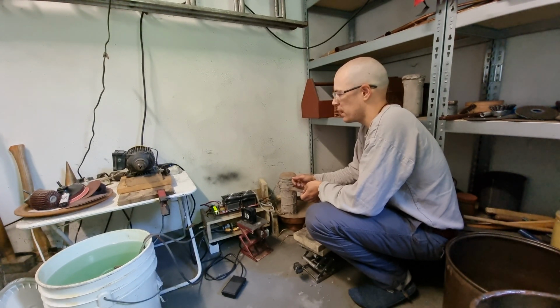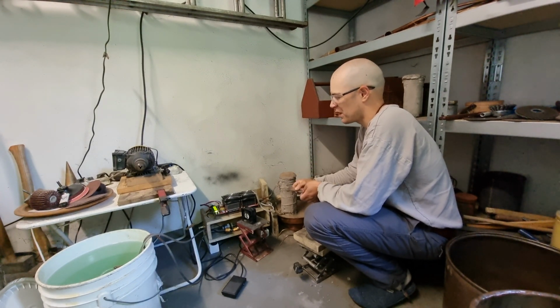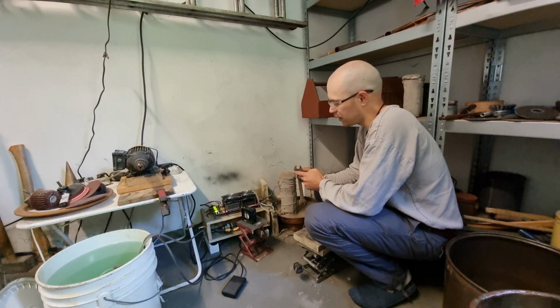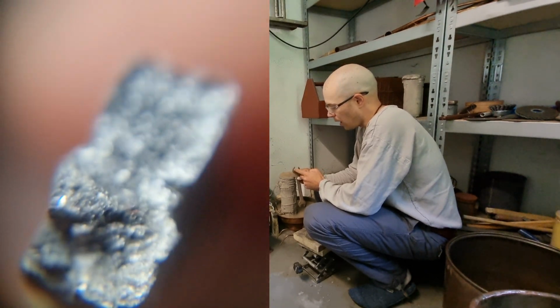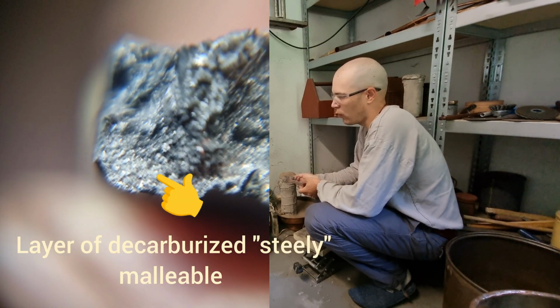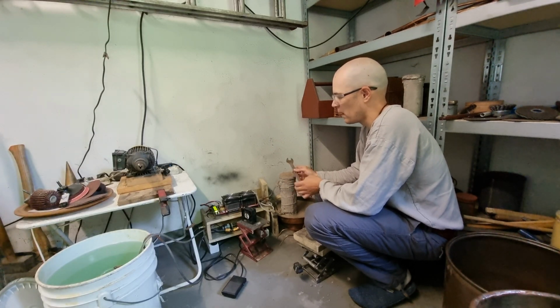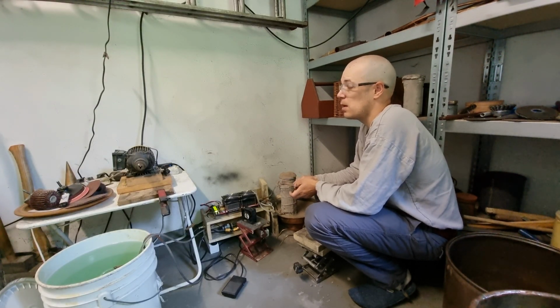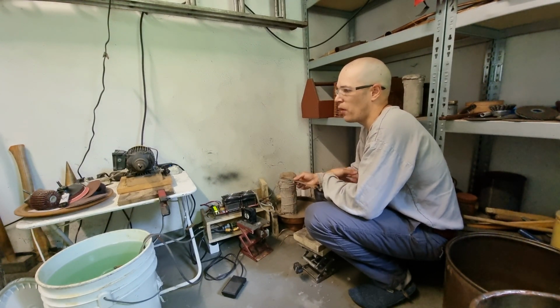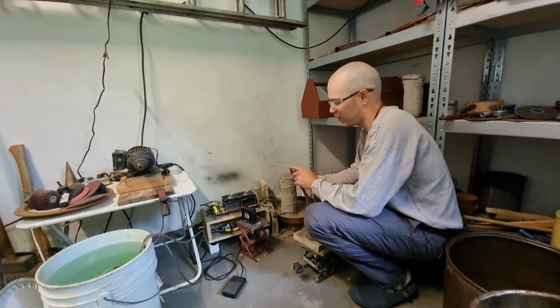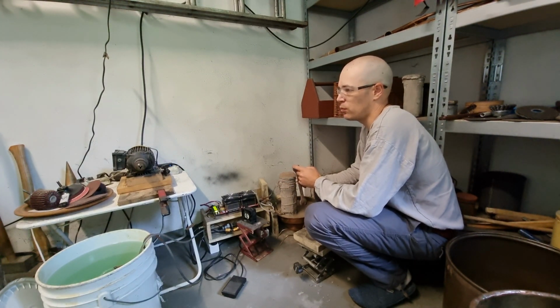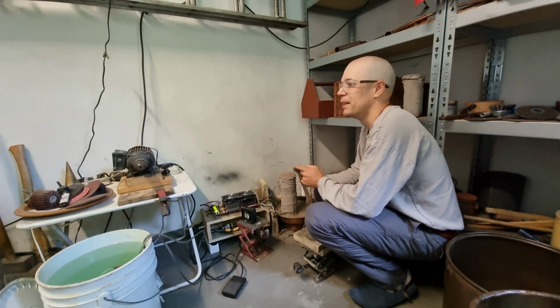Another thing is if we allow a slight excess of oxygen, then we also start to see that slowly on the surface the carbon starts to burn off, and we get a steely layer that over time starts to grow inside that material. So if we let it run for long enough, we can then also convert this black heart malleable cast iron to white heart malleable cast iron, which is essentially a malleable cast iron where all that carbon got burned off by the diffusion process on the surface of the iron. At the elevated temperature, the carbon starts to burn off, and then by an equilibration process in that material, by migration of carbon atoms inside that iron, we slowly can reduce and burn off more or less all that carbon inside the iron.